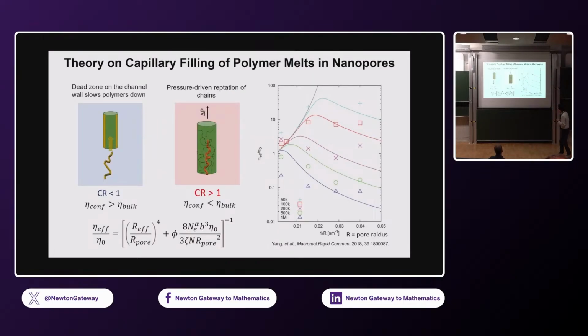So it was interesting that when we were doing this study, we came across this study, which was done by Zhou, and also in collaboration with Masao Doi, who was a close collaborator of Sam Edwards. What they've done in their experiments is that they used aluminum oxide membrane. So these have cylindrical pores, very well-defined cylindrical pores. Okay, and they did pretty much the same experiment using, in this case, polyethylene oxide to induce capillary rise.